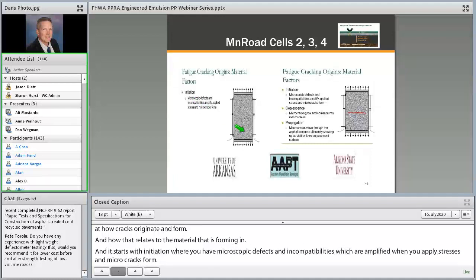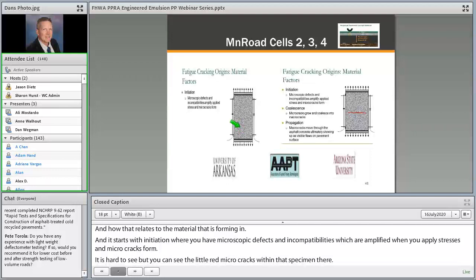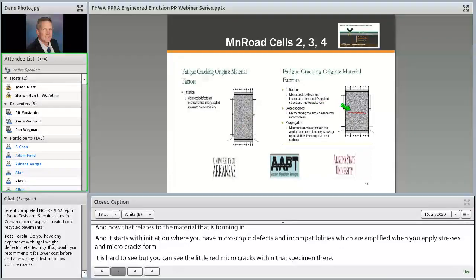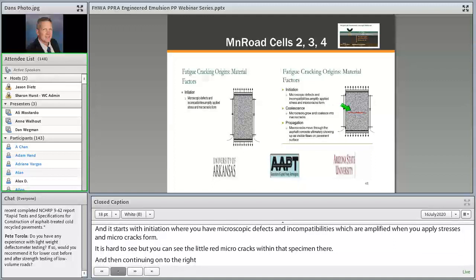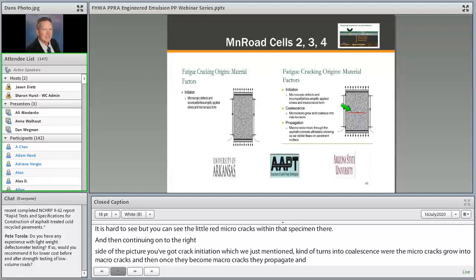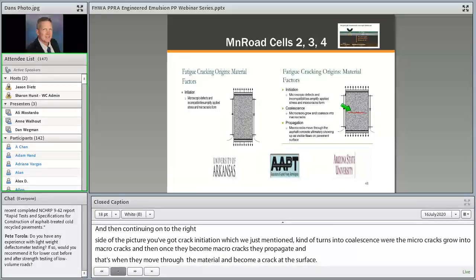And then continuing on to the right side of the picture, you've got crack initiation, which we just mentioned turns into coalescence, where those microcracks grow and coalesce into macro cracks. And then once they become macro cracks, they propagate, and that's when they move through the material and become a crack at the surface. And that would be how a load-related crack initiates at the bottom, moves through the material, and creates a crack at the surface.